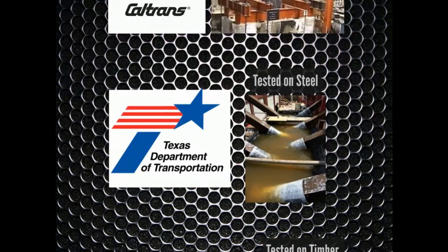The system was also tested on steel piles by the Texas Department of Transportation. They had these steel pile samples that they simulated deterioration by cutting out sections of it to significantly weaken those piles. And then they had us wrap the samples underwater with PileMedic system and inject grout. And then they removed those piles, put them into a press to test the actual capacity, and they did find that the piles were able to be restored to their original capacity.